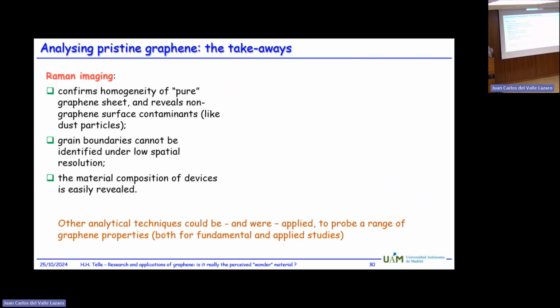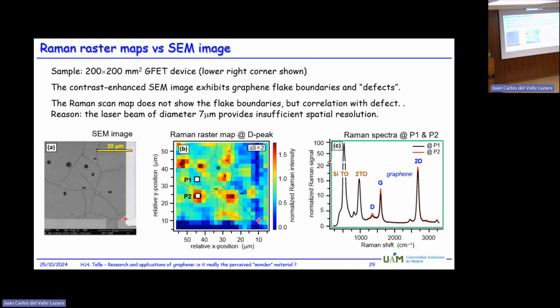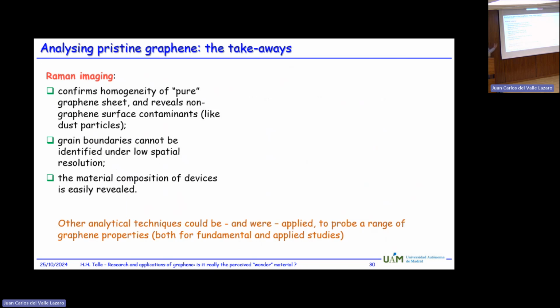But if we look back at this image here, that is the dimension, 20 microns. And if you look at some of the features here, they're well below 1 micron. So Raman imaging will not be able to resolve that. So you also may need, in addition to your Raman spectroscopy, other techniques to actually fully characterize your sample.